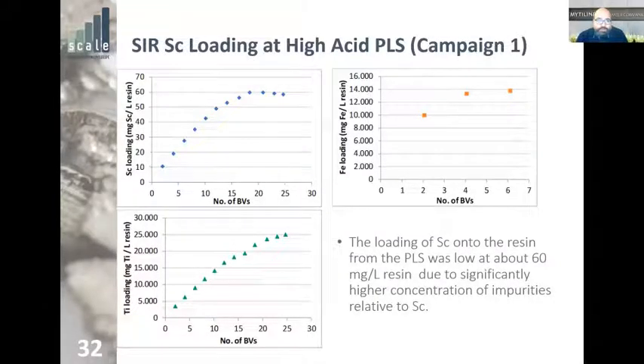So you can see that in this pregnant liquid solution, we have a very low loading capacity for scandium. You see, after 15, 20 bed volumes, the resin can no longer add more scandium. It has just loaded about 60 milligrams per liter of resin, while at the same time it holds more than 14,000 milligrams of iron per liter and 25,000 milligrams of titanium per liter. So in other words, this does not work for such low scandium content and such high impurity in the pregnant liquid solution.